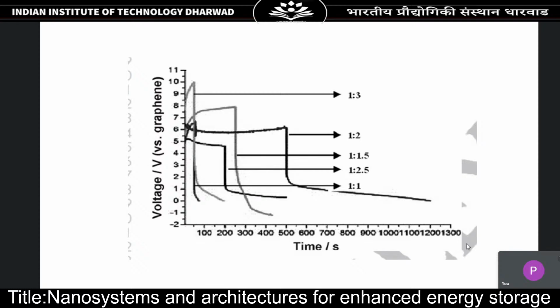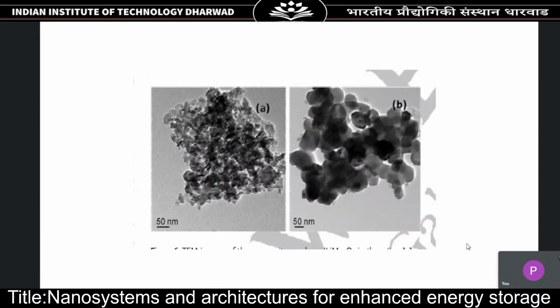So we have actually varied the ratio of lithium manganese oxide and graphene. And you can see that the ratio 1:2 shows a very optimum behavior where you can almost see a flat voltage profile, and then you also have a quick discharge. So this was taken as one of the better compositions for the device.